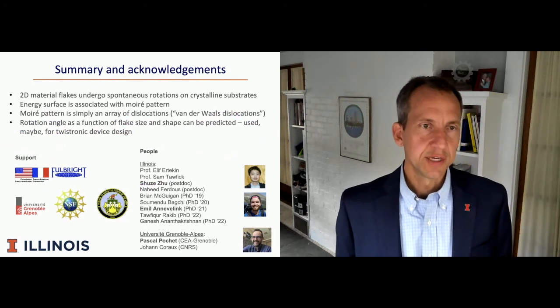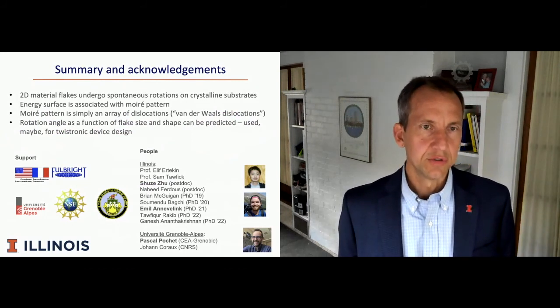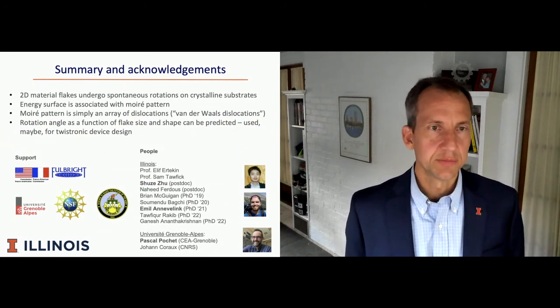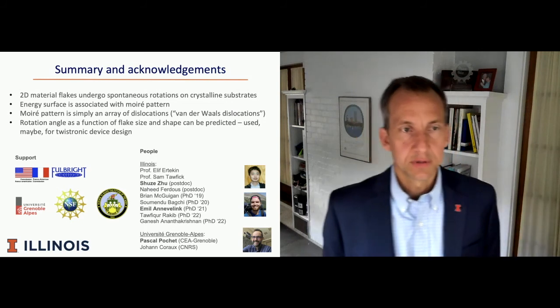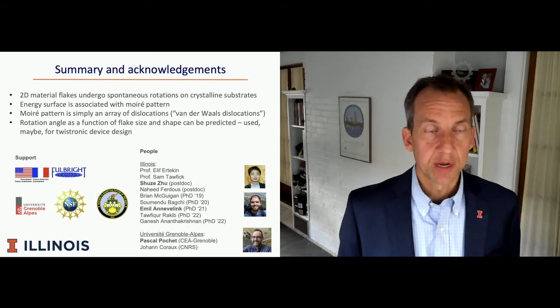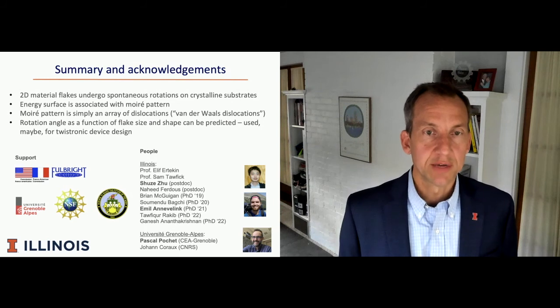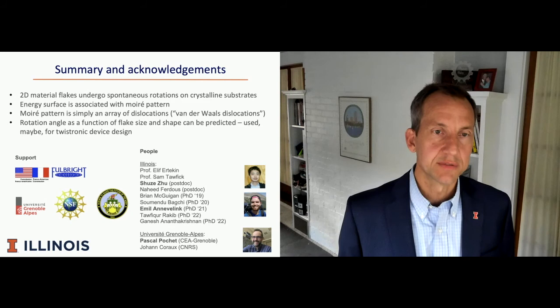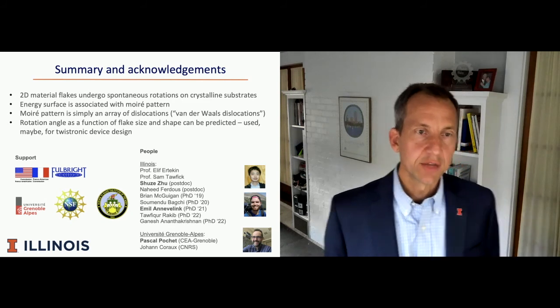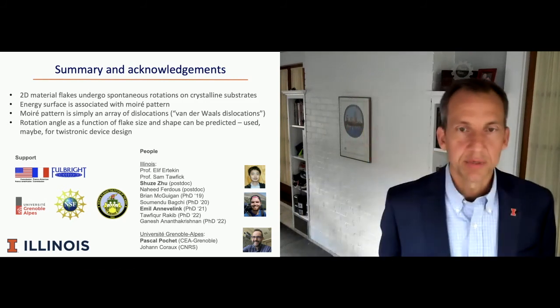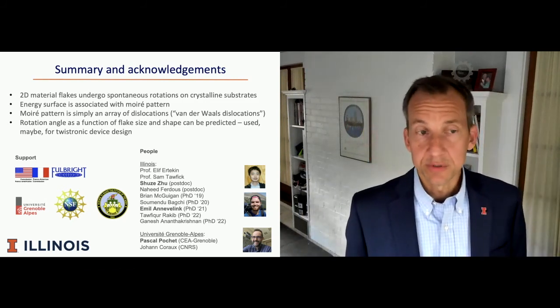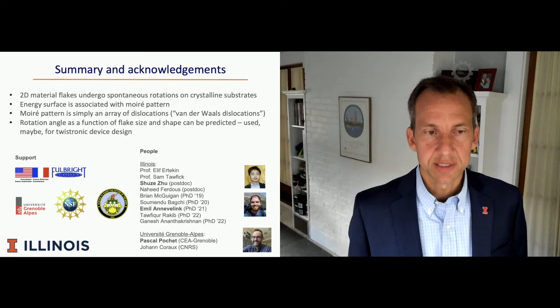The 2D material flakes that we're studying do undergo these spontaneous rotations in order to minimize their energy when they're on a crystalline substrate or on another crystalline 2D layer. Clearly, the energy surface is associated with the moire pattern, and the moire pattern is simply an array of dislocations, and that's really what has captivated our interest in this problem for some time. The rotation angle is a function of flake size and shape, and it can be predicted and may be used, we believe, for twistronic device design.